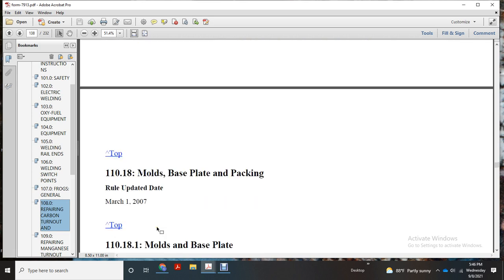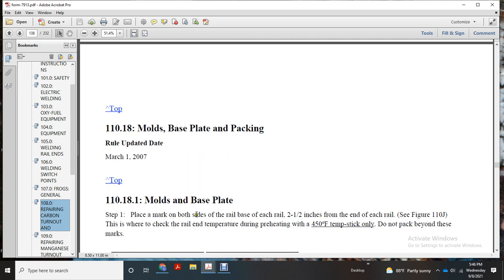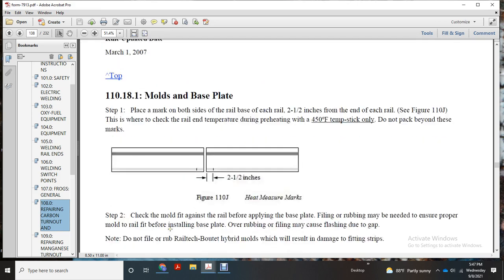Mold and base plate packing. Place markings on both sides of the rail base, 2.5 inches from each end of the rail. See figure 110 J. Check the rail end temperature during the preheat of 450 degrees with a temp stick only. Do not pack beyond these marks.